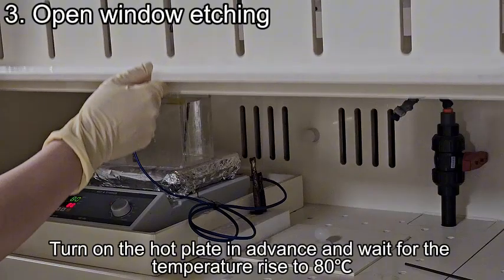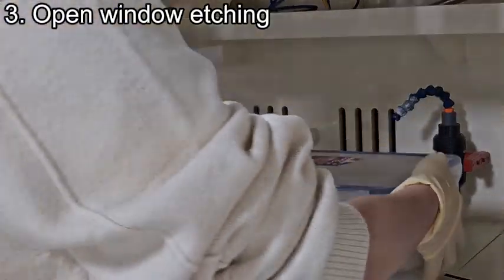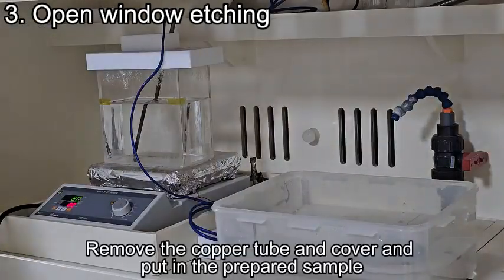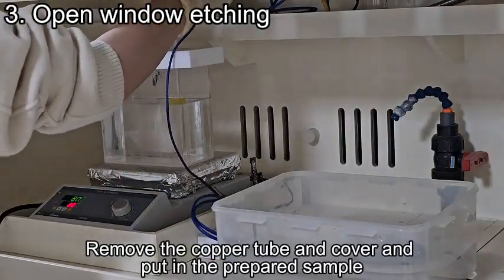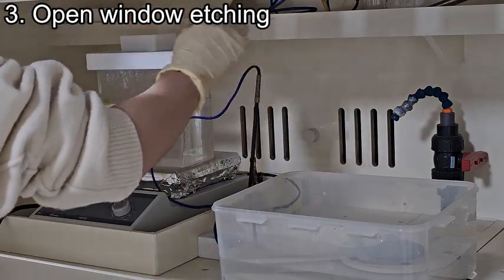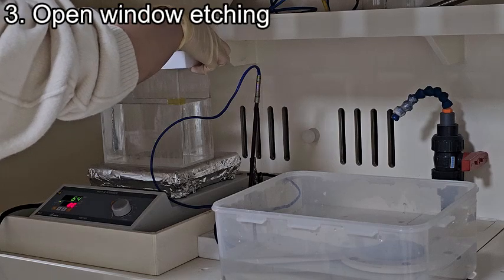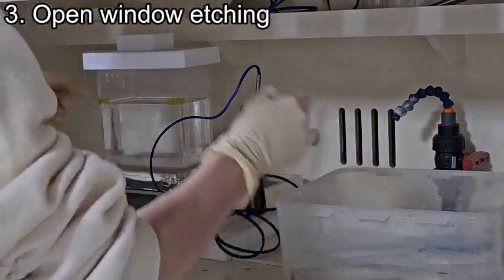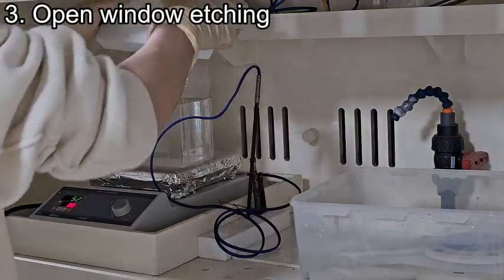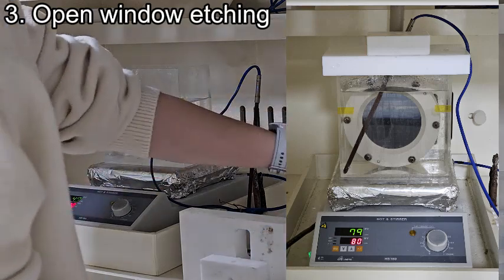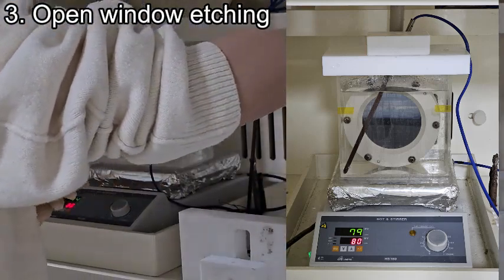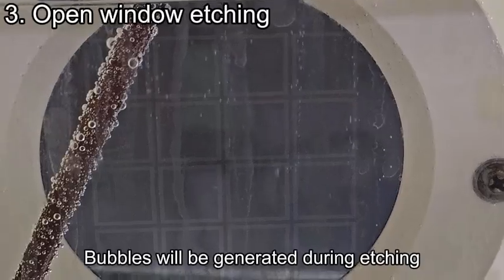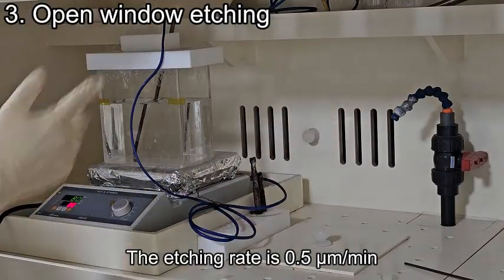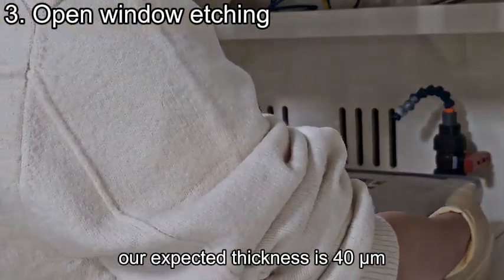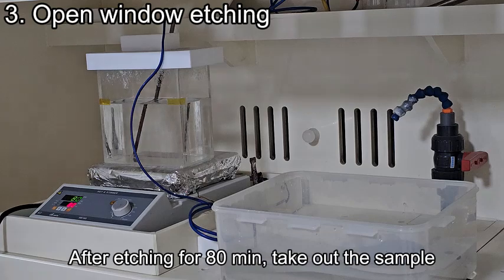Turn on the hot plate in advance and wait for the temperature to rise to 80 degrees centigrade. Remove the copper tube and cover and put in the prepared sample. Bubbles will be generated during etching. The etching rate is 0.5 micrometers per minute, meaning our expected thickness is 40 micrometers. After etching for 80 minutes, take out the sample.